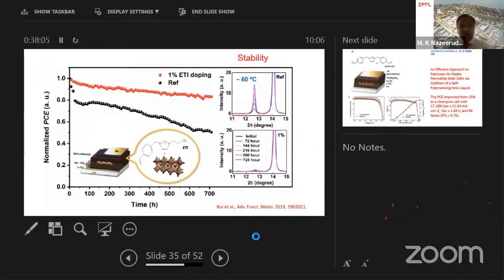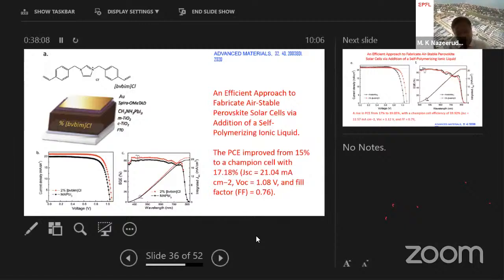Okay, the next slide shows another ionic liquid as an example, because this gives you the strength of the materials development. Here is the new ionic liquid with a double bond, so you can polymerize this double bond group. At 80 degrees temperature, these ionic liquids self-polymerize. Here is the perovskite solar cell configuration, similar to before, but we have intentionally selected a very unstable perovskite, methyl ammonium lead iodide, and we use this ionic liquid at 2%. Using this 2% ionic liquid, we obtained 17% efficiency. The reference sample is only 15% efficiency.